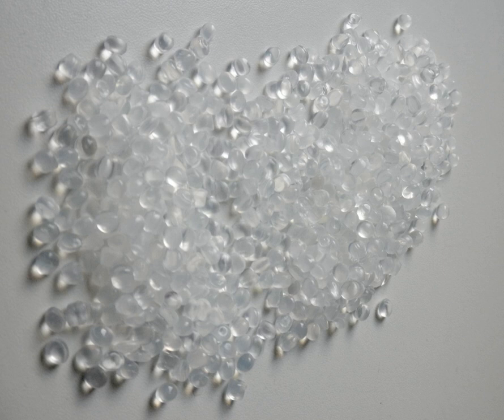The production of these trace gases from virgin LDPE increases with surface area and time, with rates at the end of a 212-day incubation of 5.8 nmol/g⁻¹d⁻¹ of methane, 14.5 nmol/g⁻¹d⁻¹ of ethylene, 3.9 nmol/g⁻¹d⁻¹ of ethane and 9.7 nmol/g⁻¹d⁻¹ of propylene. When incubated in air, LDPE emits gases at rates approximately 2 times and approximately 76 times higher in comparison to water for methane and ethylene, respectively.